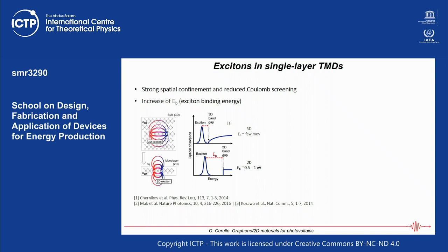In these 2D materials, the exciton binding energy increases enormously for two reasons. First, the two-dimensional quantum confinement: you have a semiconductor only one atomic layer thick. Second, in a bulk material the field lines of the electron-hole Coulomb field see the dielectric constant of the semiconductor, providing screening. But in a material only one layer thick, the field lines go outside where there is essentially no dielectric screening — the dielectric constant is approximately one — so there is no screening from the medium. This increases the exciton binding energy by two orders of magnitude, from a few meV in normal semiconductors to hundreds of meV, up to 1 eV.